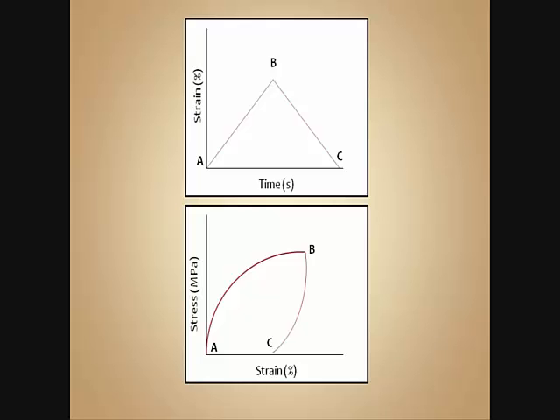Instead of unloading our sample down to 0 strain, we're loading it to 0 force. Because we're in the quasi-elastic region, we're expecting some residual strain left over. If our material performs perfectly elastic, 0 force will result in 0 strain. But like I said, we're expecting some sort of residual strain left over. If we were to unload to zero strain, we probably would place our sample in compression.